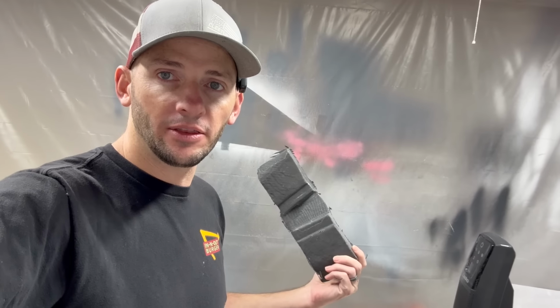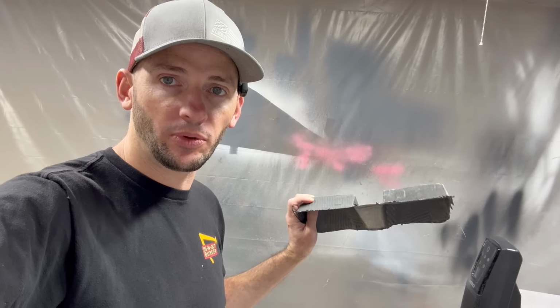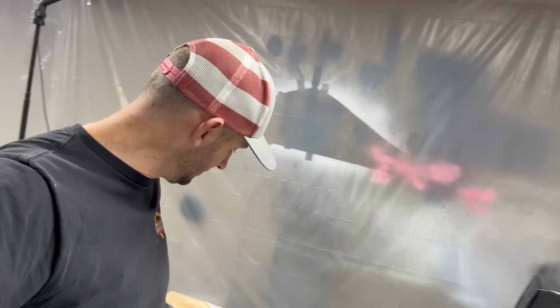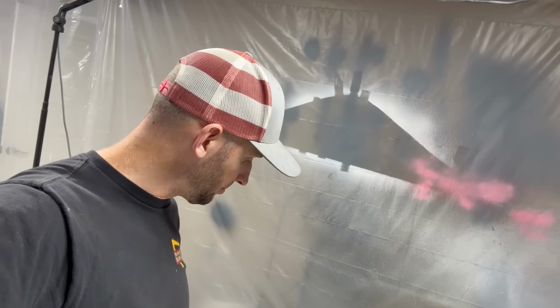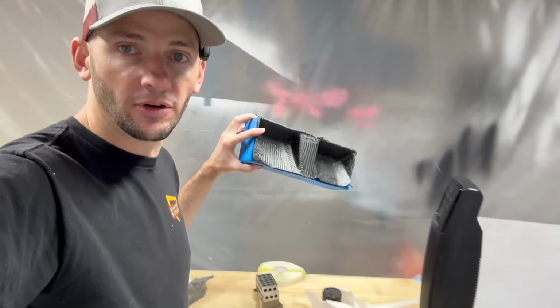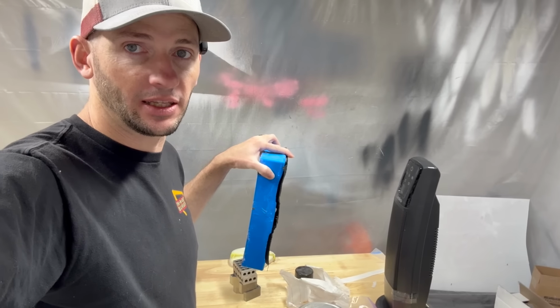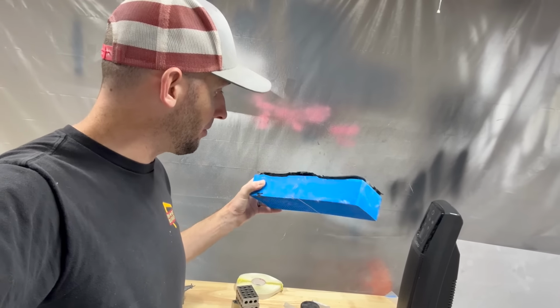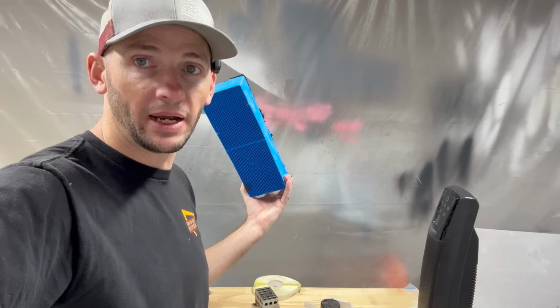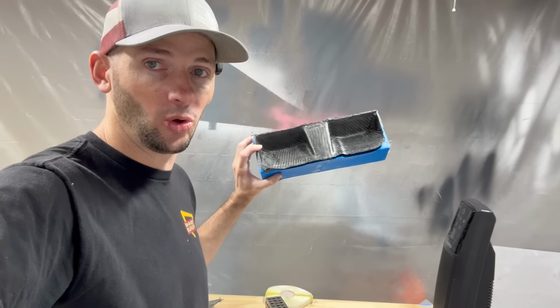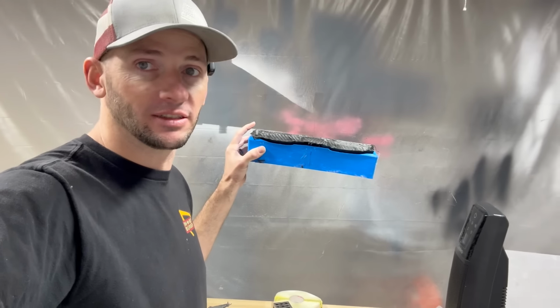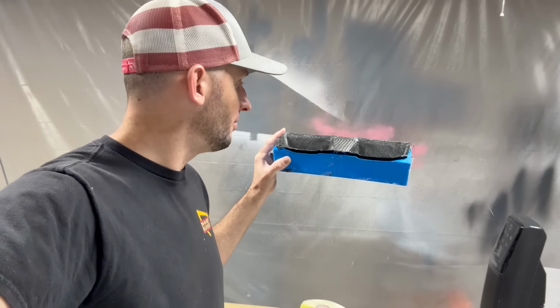And there is the part. The whole demolding process was relatively uneventful. I did actually put the part and the mold in front of a space heater and just kind of let it post cure, fully aware that the PLA mold might actually warp, which it did a whole lot. The part actually doesn't fit in the mold anymore at all.